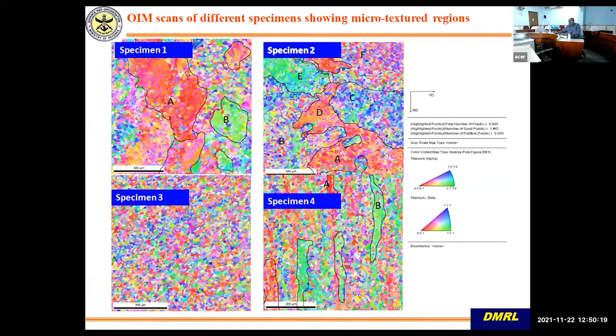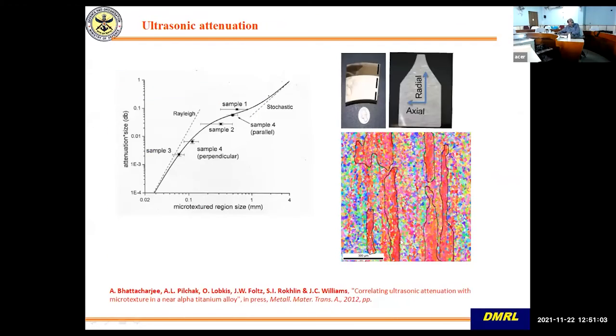But when we do a microtexture scan, you can see that the four processed specimens are entirely different. You can see this specimen 1 has got very large regions of similarly oriented material. Specimen 2 also has, whereas specimen 3 has randomized orientation. Different grains are oriented differently, and this has got the orientation as stringers running from bottom to top. So ultrasonic signal was sent in this direction from left to right, and then what I did is I plotted the size of the microtexture region in this direction versus attenuation, that is non-dimensional microtexture region size versus attenuation.